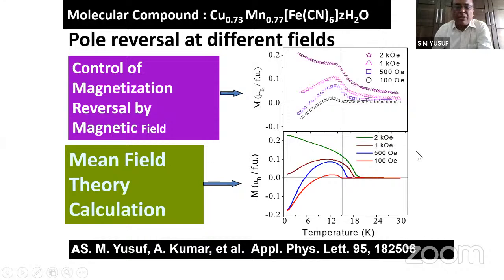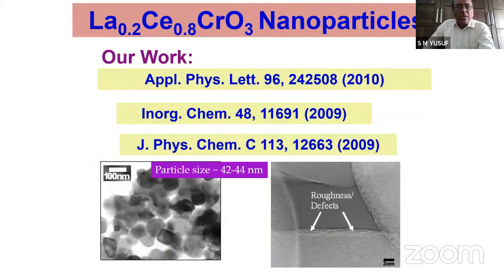See, when you do mean field calculation under field, we take the external Zeeman energy as well as the internal field both. But for the neutron diffraction case, which I showed earlier, there we take only the internal field because externally we did it without applying any magnetic field. This has been observed even in nanoparticles.